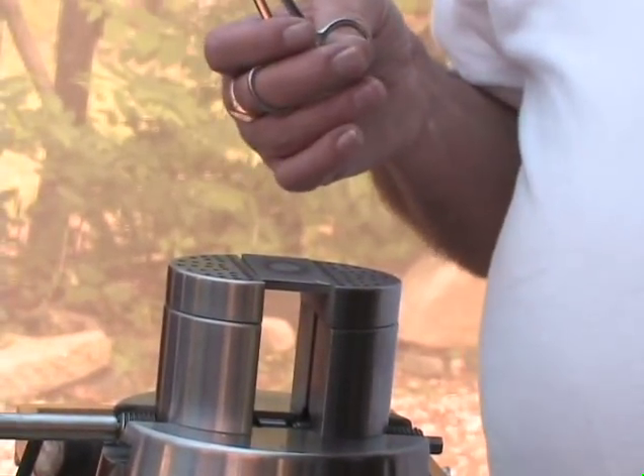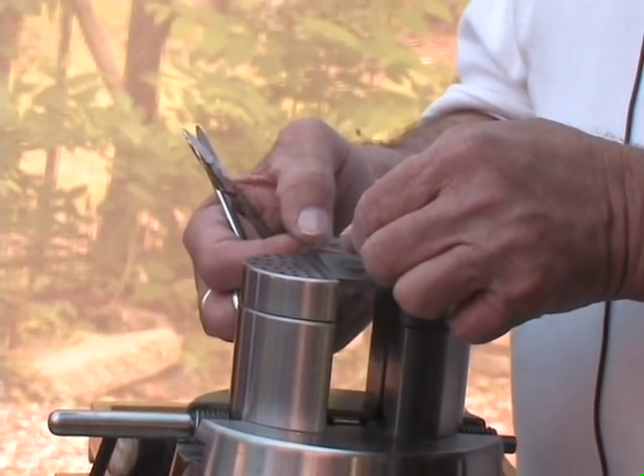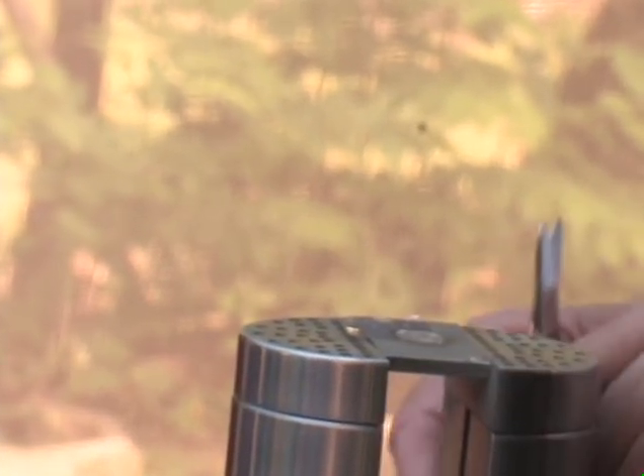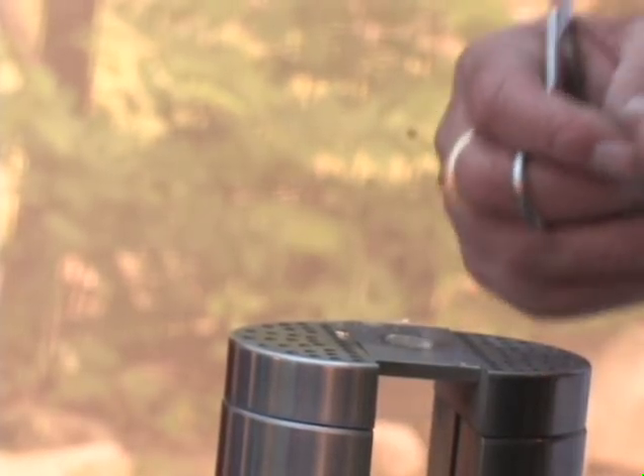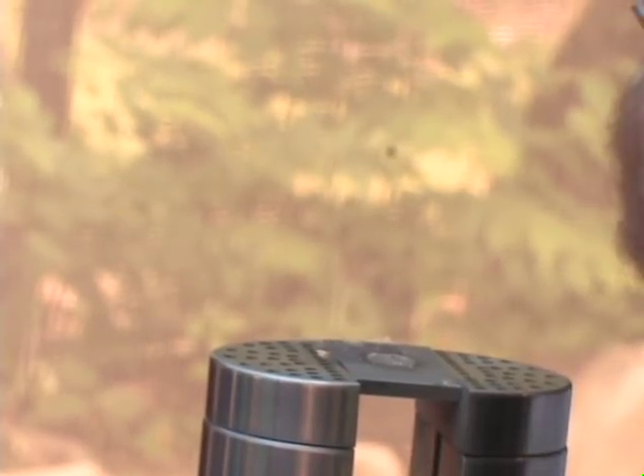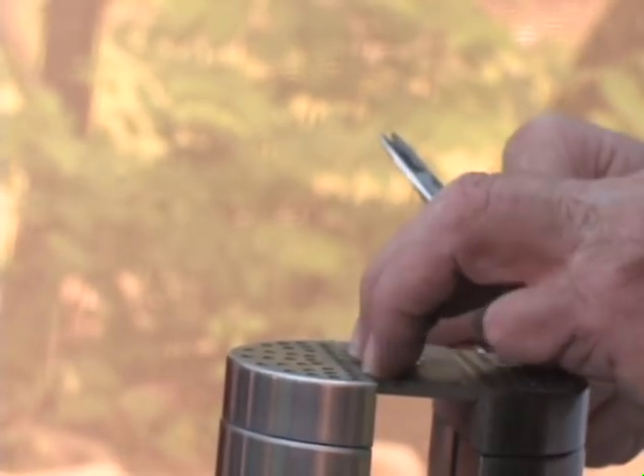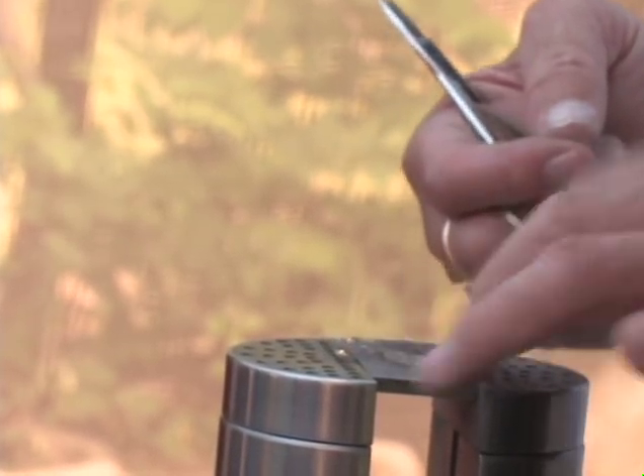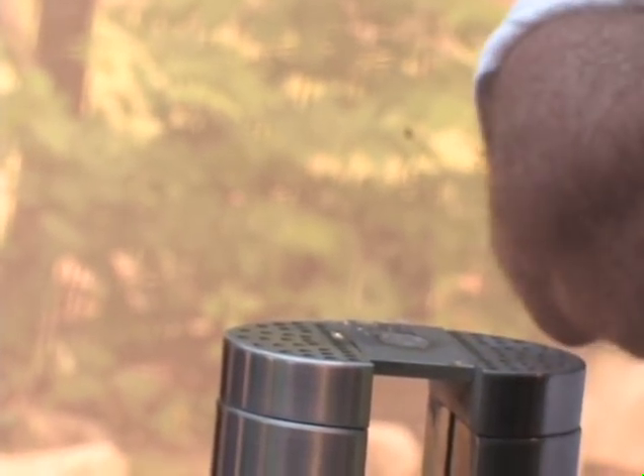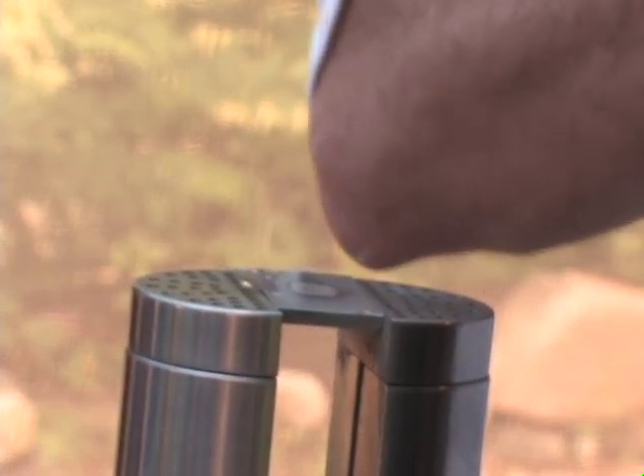About 4.5, yeah, 4.5 to. If you err, I like to err on the thicker side. What if it is thicker? It won't make an awful lot of difference. If you went to 6 or 7, then you're starting to get a little bit thick, and it may squash out and not push down into the crevices. If you go to a thicker gold, then your cross hatching and the rest of the stuff should be deeper.